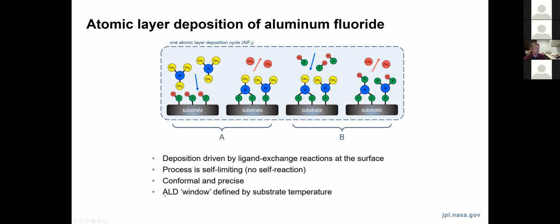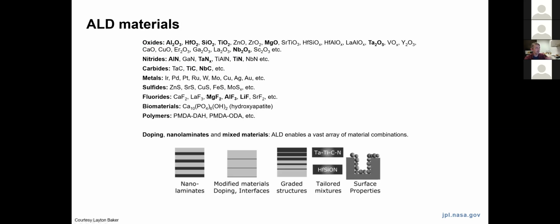You typically get a substrate temperature window that enables these reactions to proceed in a self-limiting manner, and you get extremely reliable deposition rates as long as you operate within that window, which is typically in the range of 100 to 200 C. So still compatible with the end-to-end processing. And because it's sort of this gentle chemical interaction with the surface, it does not damage the delta doping layer underneath.